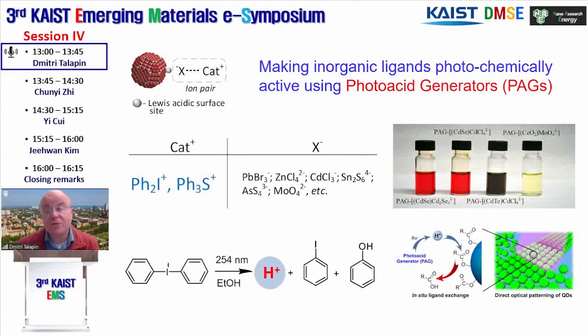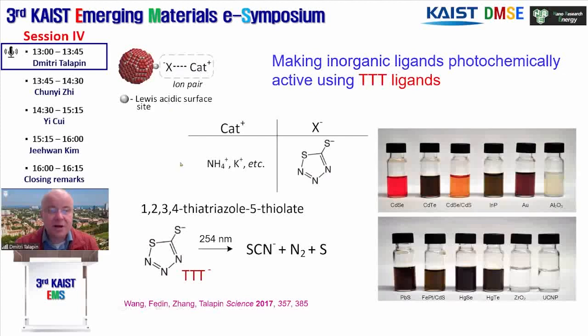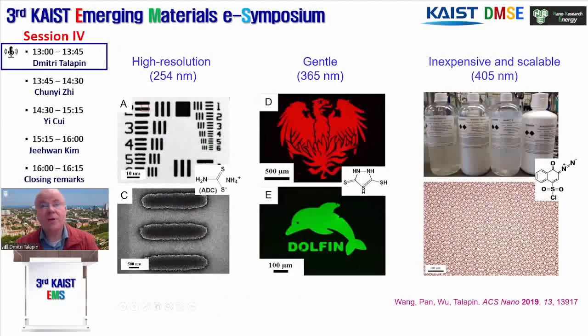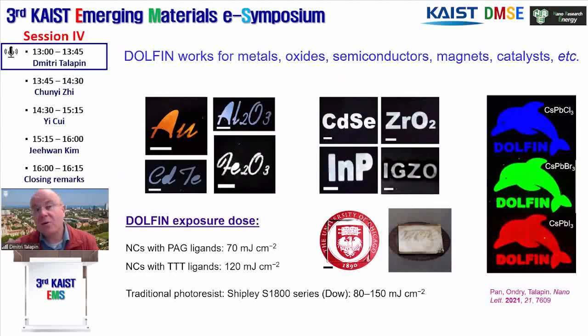And there are many approaches. Our historically first approach for engineering photochemically active ligands was using photoacid generators, or PAGs, that allowed us to change solubility of particles in the exposed versus unexposed areas. But it's just one approach. You can use photodecomposition of heterocyclic compounds. You can use all kinds of other chemistries that are tailored to certain wavelengths and serve different purposes. For example, if you want to push resolution, you need to design ligands that will be photochemically active in deep UV. And then you can make really small sub-micron patterns. You can use i-line molecules sensitive to the i-line, or 365 nanometer light, to make it more gentle and minimize damage of quantum dots. Or if you want to push cost as much as possible, you can switch to 405 nanometer and use sol-gel compounds, and then it becomes much more cost efficient.